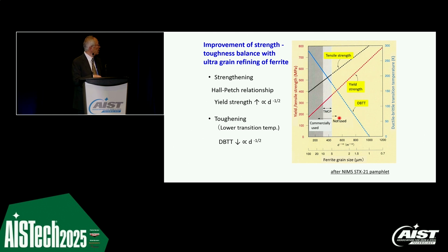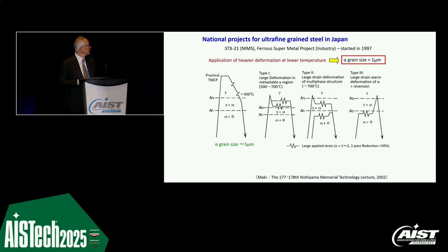So at the beginning of this national project in the late 90s, the normal transformation ferritic grain size is about 10 microns. Applying TMCP, we can go down to 5 microns. But if you go for a grain size less than 1 micron, we can actually double the strength and also obtain a really low transition temperature. So that was the main target. So this is the industry-oriented national project, super steels, super metals project.